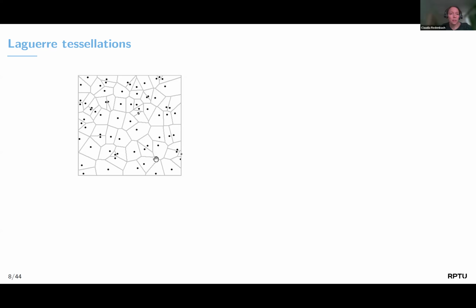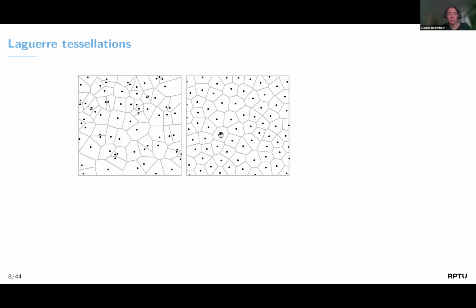If you look at this cell system, you see that the cells have very diverse sizes and shapes. You see rather small ones, rather big ones. You also see very small angles here, for instance. And that's not very consistent with the laws of foam formation, which rather suggests that the cells should have a regular, more roundish shape with almost equal edge lengths. So if you want to move in that direction, you could arrange your generator points more regularly in space.